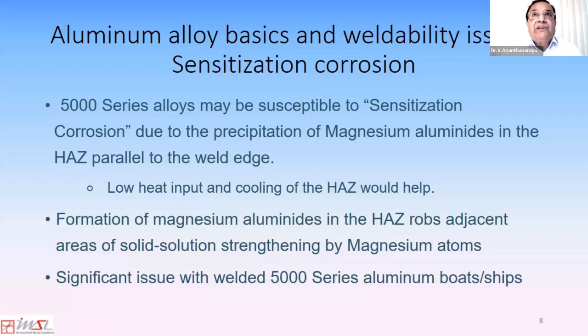I have known some aluminum ships that go into the sea, come back to the dock every 2 or 3 years, just to gouge out these sensitization corroded lengths parallel to the weld, and then deposit new weld metal and go back to the sea. And during that time, the ship or the boat is not available for service. So this is a serious problem that if the welding industry addresses, it would be a useful contribution to the manufacturing industry.